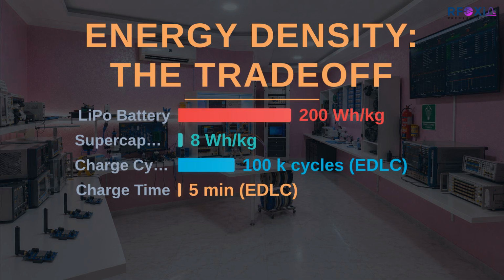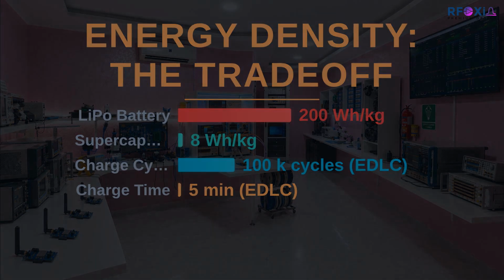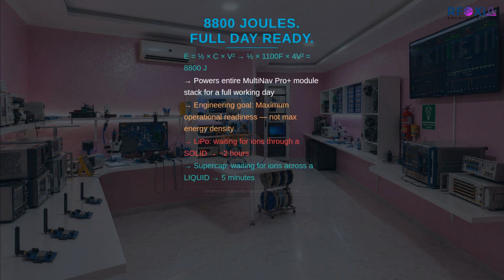Electrochemical storage, batteries, achieve energy densities of roughly 150 to 250 watt-hours per kilogram. Supercapacitors achieve 5 to 10 watt-hours per kilogram. That is a factor of 20 to 50 difference in energy density. A supercapacitor is not competing with a lithium cell on stored energy per unit mass. It cannot win that contest.